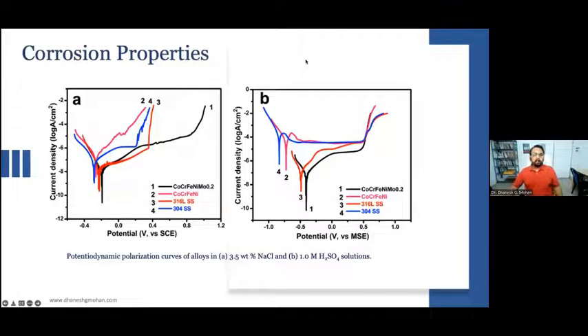And these are the corrosion properties. We conducted the potentiodynamic polarization test for these metals and compared them with three other metals. That is other alloys, not high entropy alloys: cobalt, chromium, iron, nickel, and normal stainless steel 316 and 304. We used a medium of 3.5 weight percent salt and 1 mole of sulfuric acid. In these two mediums, we found out that this material, which we fabricated using additive manufacturing, shows a superior quality of corrosion resistance. You can see over here, the first one is showing the high entropy alloy.